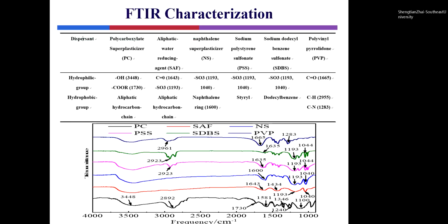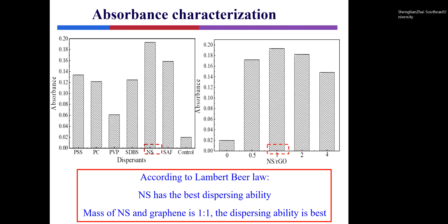This picture shows the functional groups and the chosen dispersants. We can see that these dispersants have both hydrophilic groups and hydrophobic groups. This picture shows the absorbance of the graphene in different dispersions. We can see that the absorbance of the NS is the largest. According to the number below, NS has the best dispersing ability. In addition, this picture shows the absorbance of the graphene in different concentrations. The result shows that when the mass ratio of NS and graphene is 1:1, the absorbance is the largest. The dispersing ability is the best.